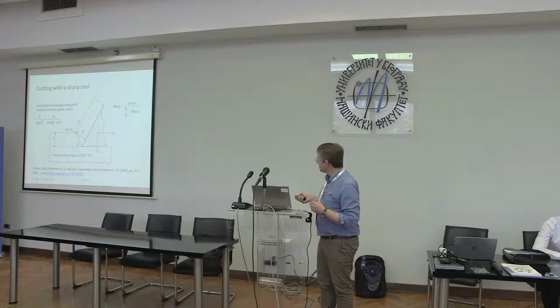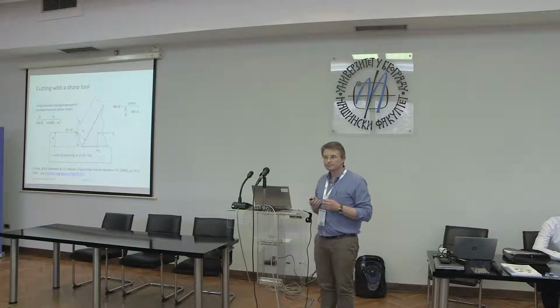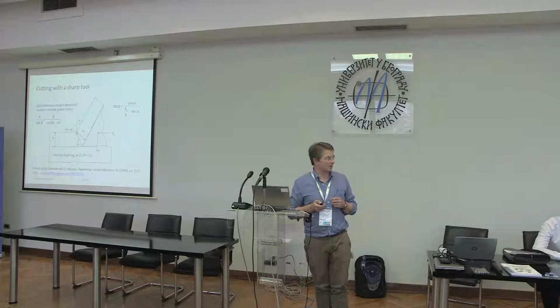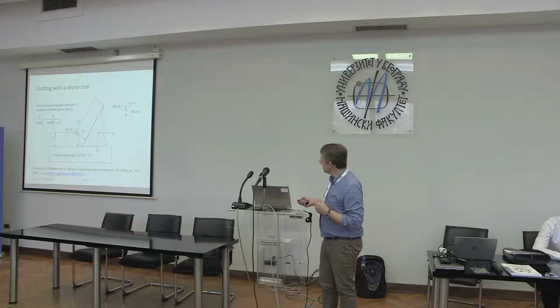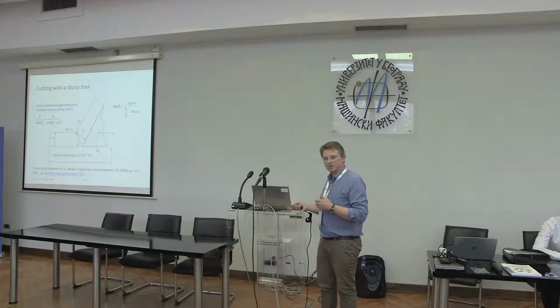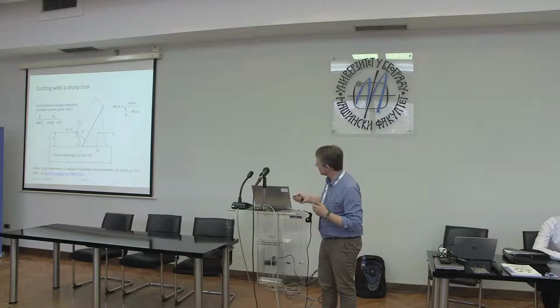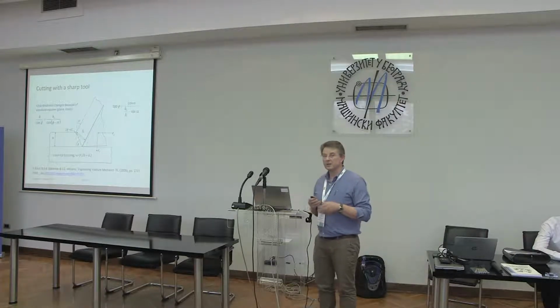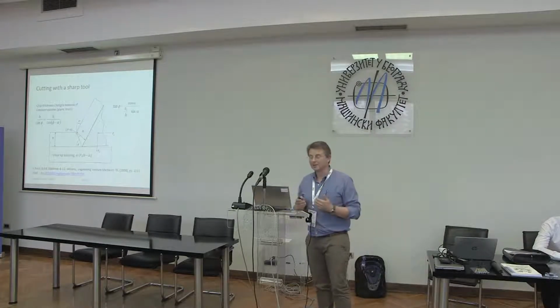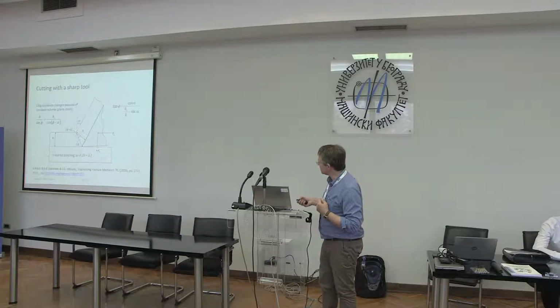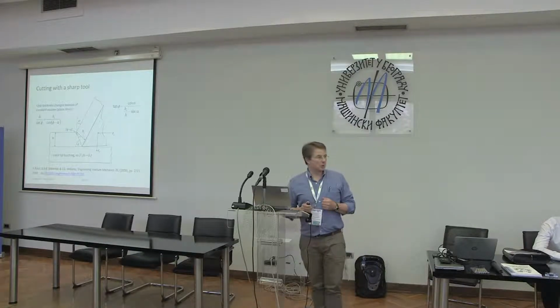So what's happening at the tip here is that we have a shear plane. So there's a plane of material which is plastically deforming. So as this chip is removed from the material, it tends to curl around actually for various reasons. It doesn't tend to come straight up the tool, it tends to curl around. And you can get interesting parameters actually by measuring the curl. Okay? But what's happening is you've got a shear plane, and the material is plastically deforming here, and this leads to a thicker offcut.